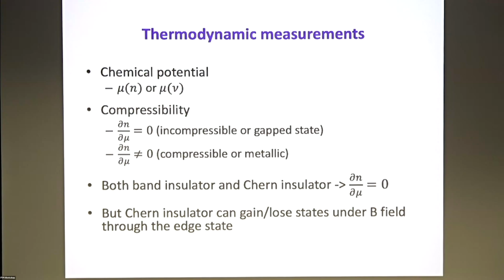If it's non-zero, it's a metallic state or compressible state. And for both the band insulator and the Chern insulators, it's an incompressible state, so this should be 0. However, the Chern insulator can actually gain or lose states under a magnetic field because of the edge states. So basically, the idea is to measure how the Chern insulator gains or loses states under a magnetic field.